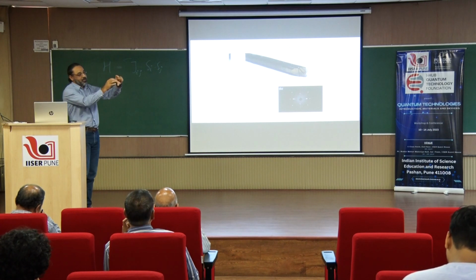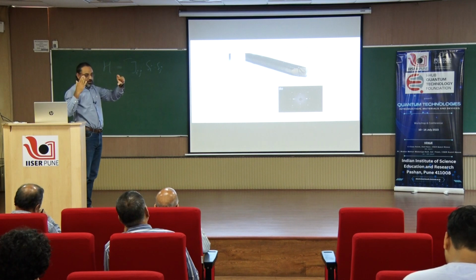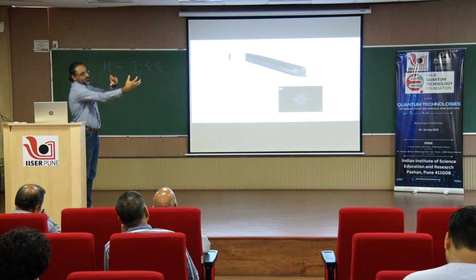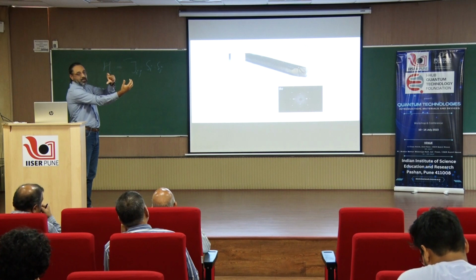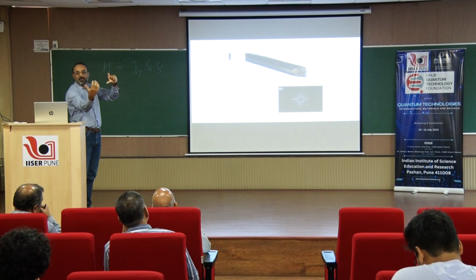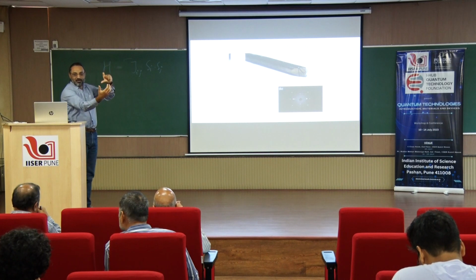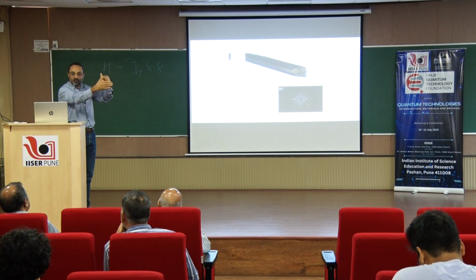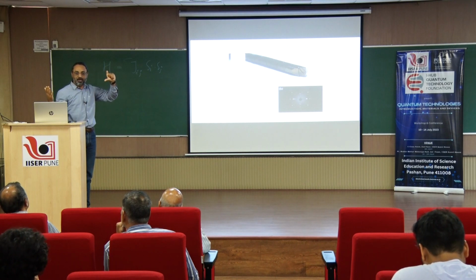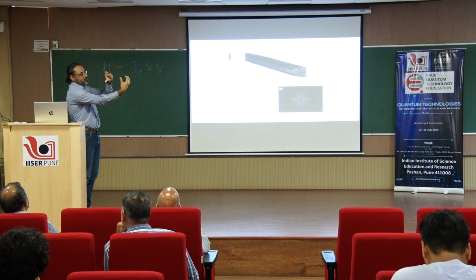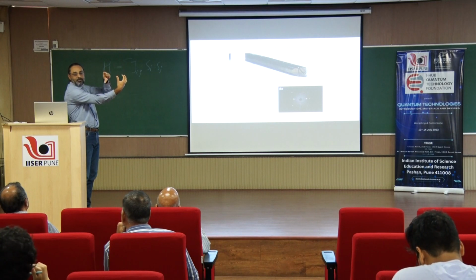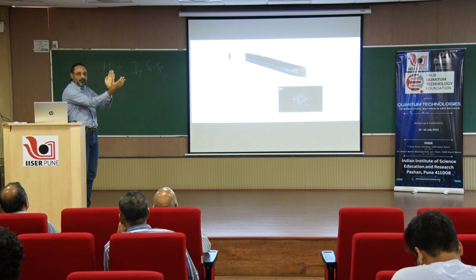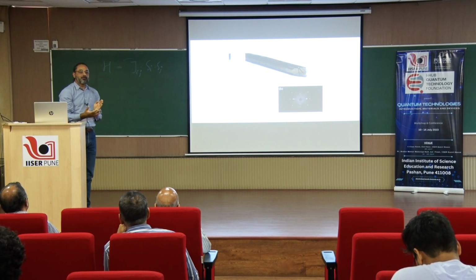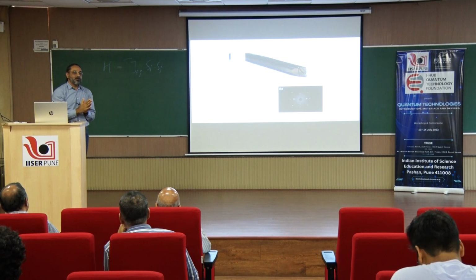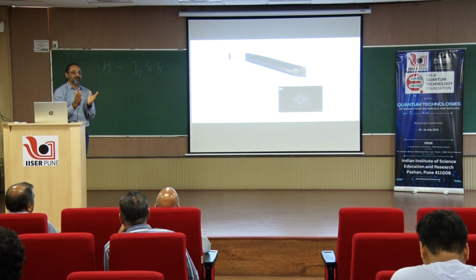So you put your crystal in such a position. This is your source. You put your detector over here, such that your detector is actually detecting a Bragg reflection from the crystal. All right. So what that means is that if you move your detector too much here or too much here, then you wouldn't see this reflection, because the Bragg reflections happen only along particular directions that satisfy the Bragg's law, right? Now, after fixing the detector, what you do is you rock your crystal a little bit around the Bragg position, okay? Around the Bragg position, you rock it a little bit, and if the crystal is a good crystal, then you should immediately see an extinction, isn't it so?